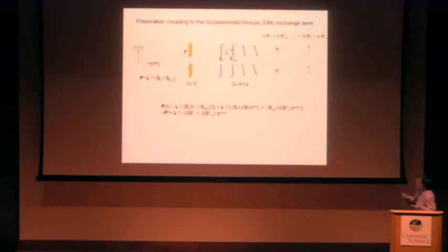So this is a simple scheme where one couples an antiphase spin fluctuation mode that appears near Q equals pi plus q to an in-phase polar mode which appears near Q equals 0. So that's a simple phenomenological model that explains how one can map a spin wave mode near Q equals pi to a lattice mode near Q equals 0 through a dynamic sort of DM interaction.